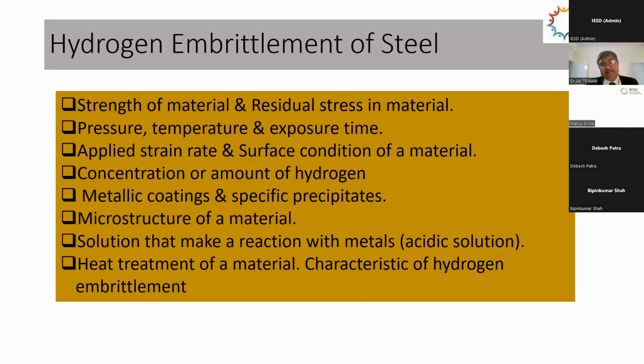Next slide, ma'am. So we conclude the embrittlement aspect: strength of material and residual stress, because when forming or welding takes place, certain stresses develop in the metal. It depends on the strength of the material, the yield stress or ultimate tensile strength, but at the same time the residual stress in the system, pressure, temperature and exposure time, as we talked about, strain rate and surface condition of the metal, whether smooth or having some irregularities, and the concentration or amount of hydrogen you are exposing the metal to. Certain metal coatings prohibit hydrogen going into the metal, and the microstructure of the material, whether ferrite, bainite or other structure. Depending on the type of structure, the penetration of hydrogen increases or decreases.